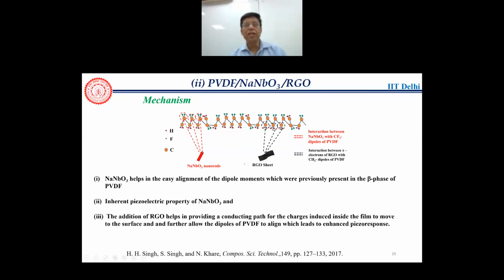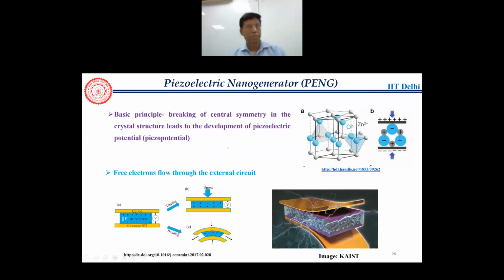So with that idea, we started working. And what was the motivation in this one? There are many piezoceramic materials like barium titanate and PZT, which has very good ferroelectric property. But the problem here is that they are brittle and not flexible. Besides that, PZT, which has very good ferroelectric property, is not very environmentally friendly. So that's why we started using this PVDF material as a host and making this nanocomposite material so that the beta phase can be enhanced.